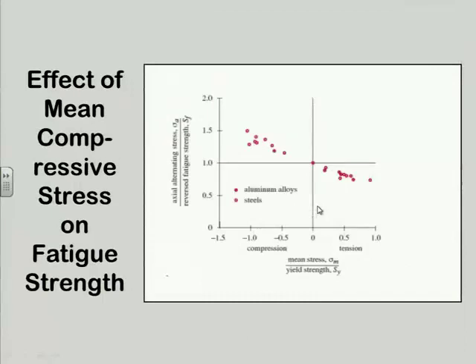Now, we've talked before about the positive effect of compressive residual stress on the fatigue case, because it tends to close the cracks. It lowers the threshold. We have to then get the tensile up above that threshold before it really is seen by the part, and all that good stuff.